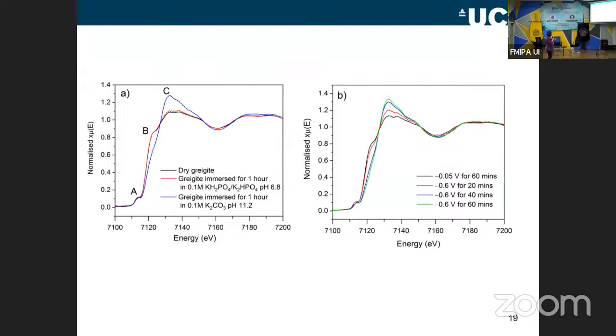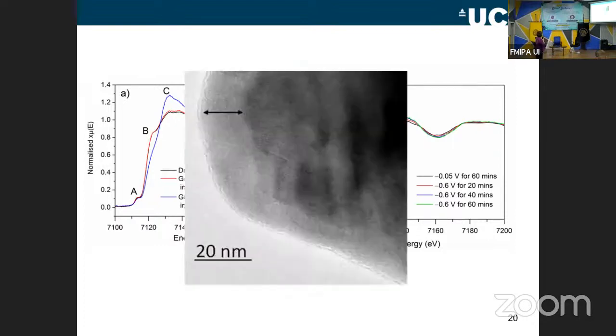And to kind of prove this a little bit, I'm going back to this spectrum. Before I told you to ignore the blue one, but you can look at the blue one now. The blue one is basically what happens if you take the greigite and you just put it for 1 hour in a solution of pH around about 11. And you can see that I've lost the shoulder and I've increased the intensity, which shows that I make the hydroxides under those conditions. And you can see the spectrum in blue here more or less matches the spectrum that I get if I apply the potential for that time. So it seems to suggest that that's what the pH is.